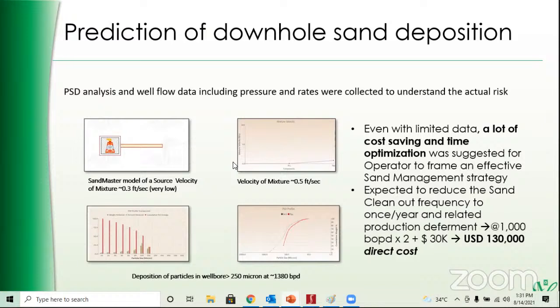So what we told them was that your velocity at the source is quite low. We gave them a limit of the velocity they need to reach in order to transport each and every particle to the surface. We told them that if they reach a liquid rate of around 1380 barrels per day, every particle greater than 250 microns will flow to the surface. That means you will have very little deposition downhole. So we decreased their coil tubing cleanout frequency from, let's say, 3 to 4 times a year to only once a year. And this is a direct cost impact of $130,000.